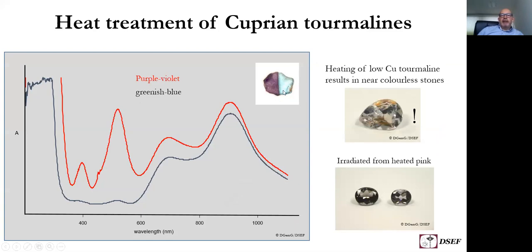Again, purple stones can be heated, and as a result of the heat treatment, you get rid of manganese absorption, leaving behind a blue, greenish blue, bluish green stone. However, in many of these tourmalines coming from Mozambique, the concentration of copper is so low that when you heat treat the stones, they get almost colorless. If you have a stone where the copper concentration is low, so that you virtually don't have any absorption here, so if you heat treat the stone, the absorption spectrum will look like this, just a straight line, and the stone then is almost colorless because all the light can go through, there is no selective absorption.